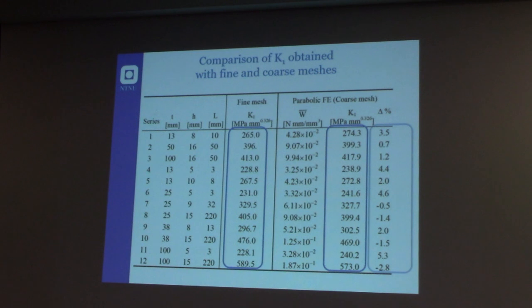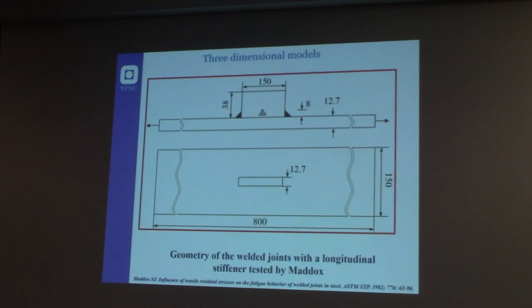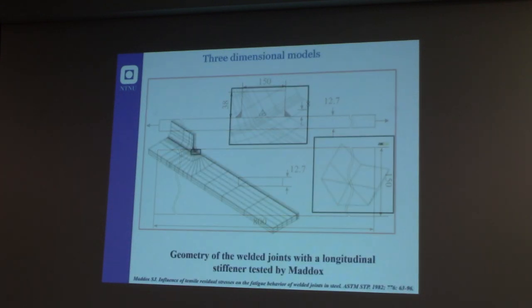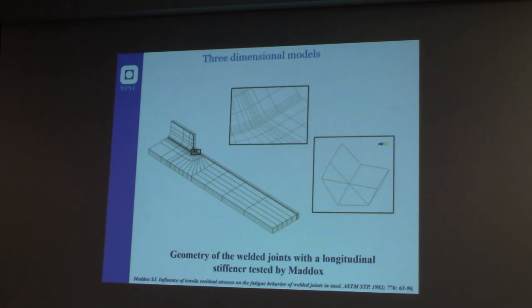And the difference that you have is very small, almost 3–4% in terms of notch stress intensity factor if you use a very coarse mesh with respect to a fine mesh. So this is very efficient. Of course, this method is very powerful if you use it for a three-dimensional component. You can use a very fine mesh like this close to the notch tip, and you can evaluate the strain energy density in a three-dimensional model very easily with a very light model.